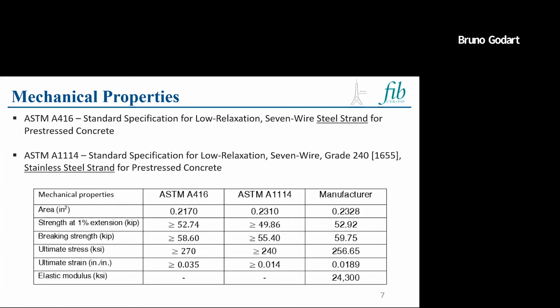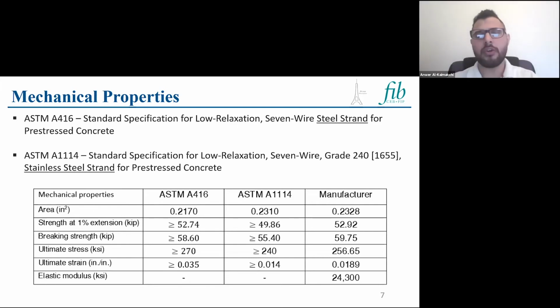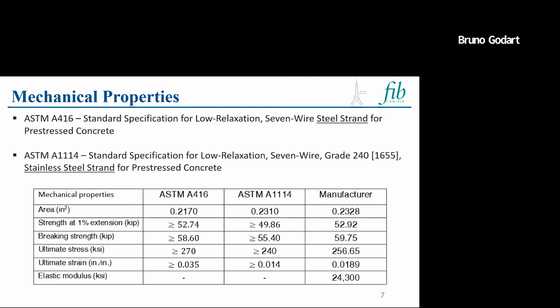I think it's right for capacity, ultimate capacity. But for deflection, it's more difficult to say that because first, your girder number 1 was stopped before complete failure. So it means that there was still a capacity of deformation, probably. And then when we look at the behavior law of carbon steel, we have a greater ductility than with stainless steel. So it means that in the girder, we can have more ductility with carbon steel than stainless steel. That's the main issue in design. Yes, correct. Yeah, the main issue in design.